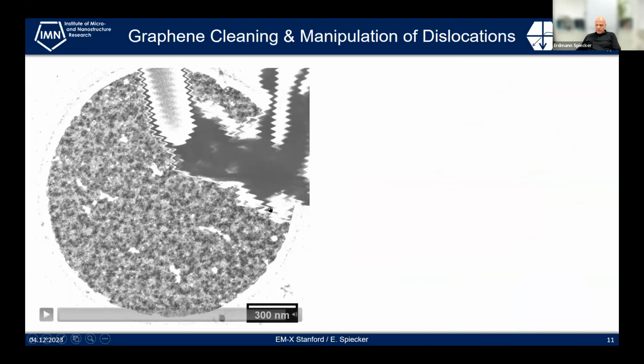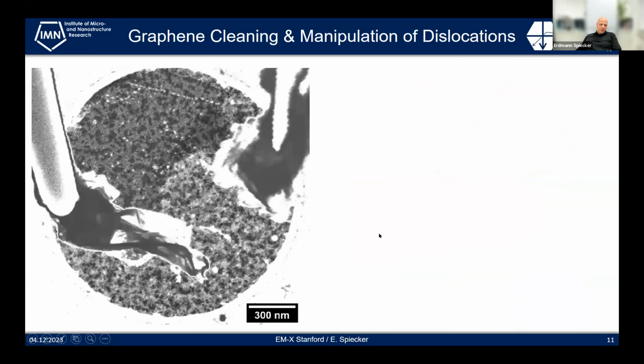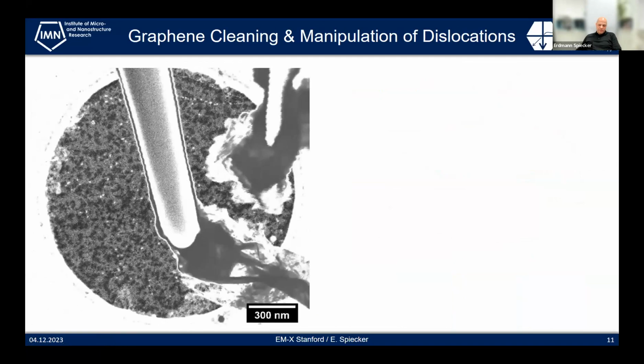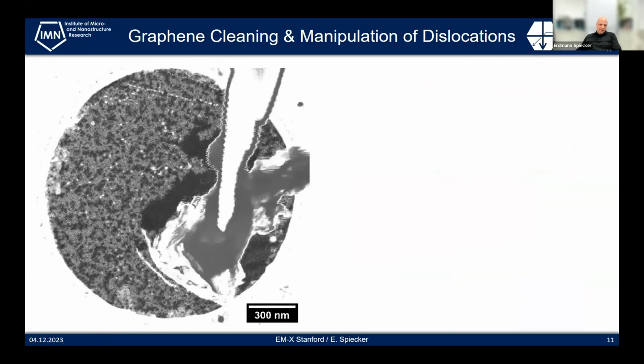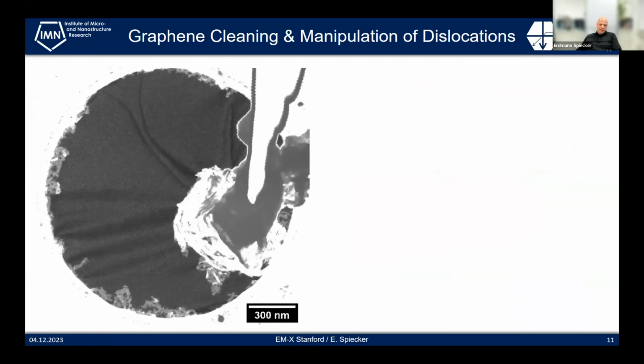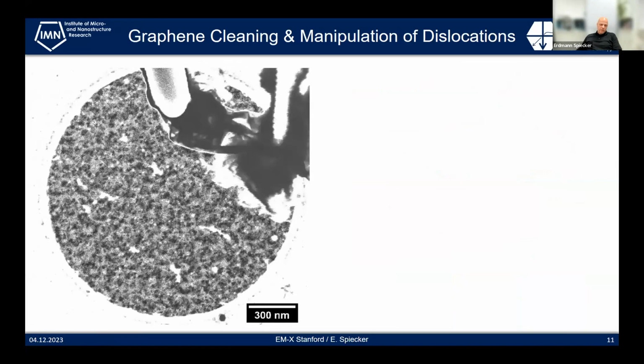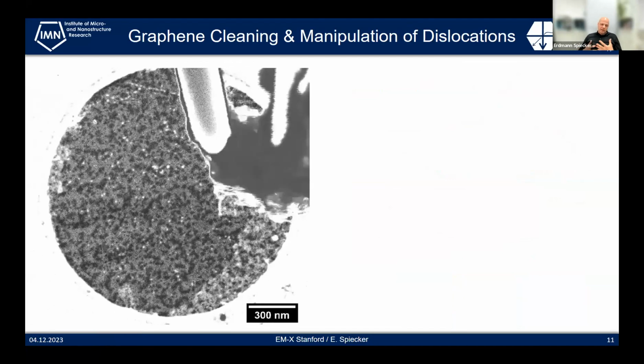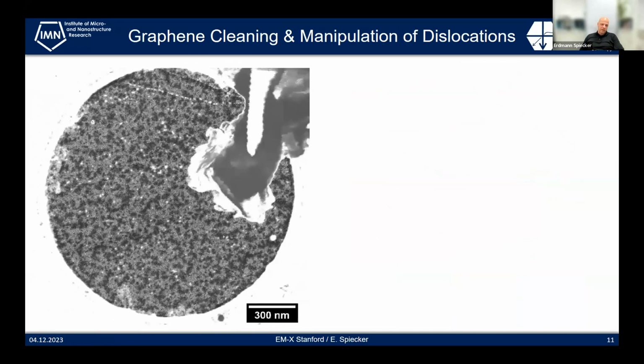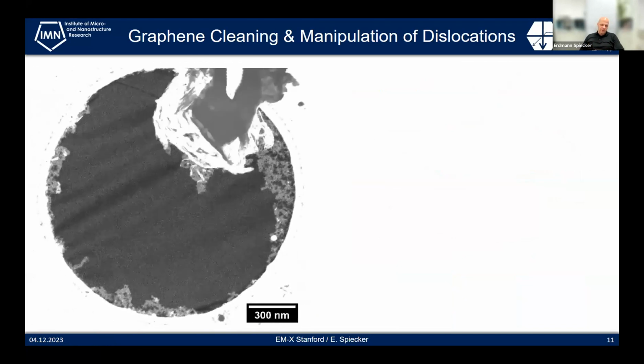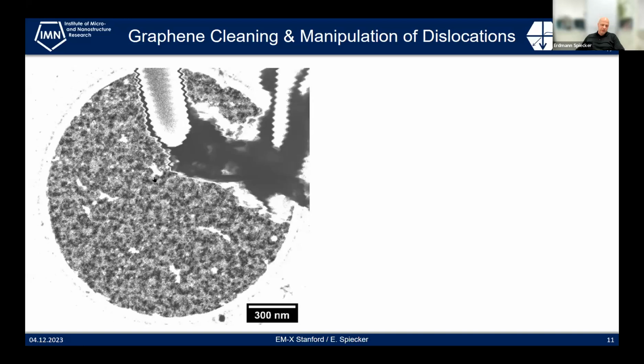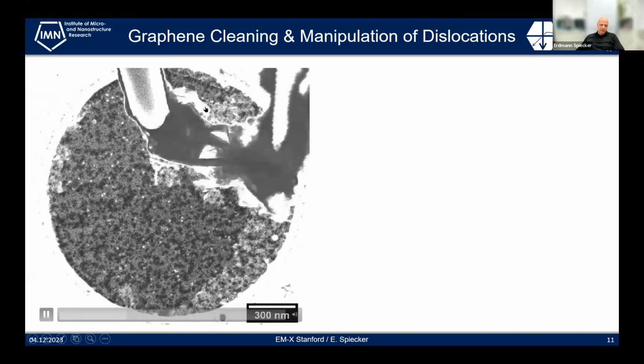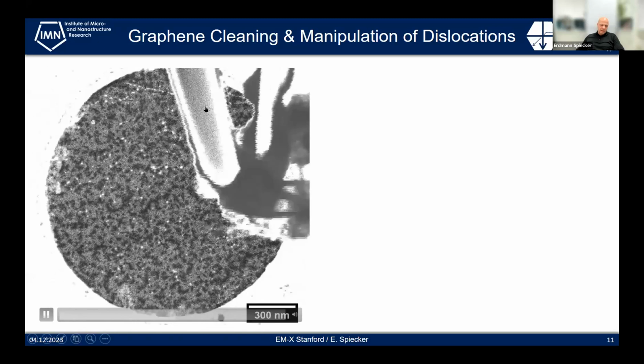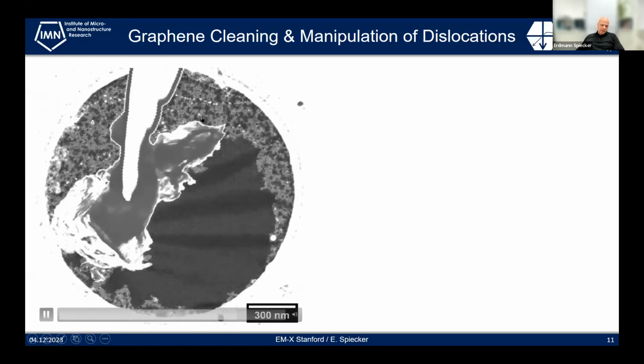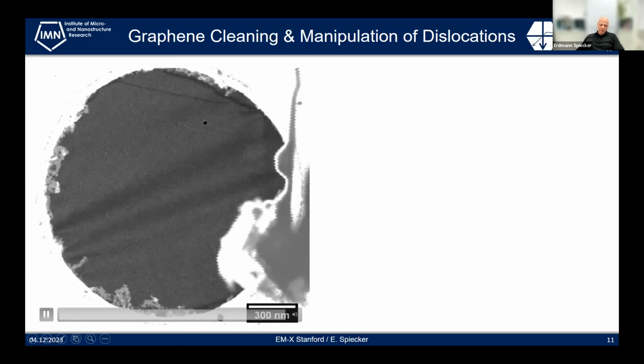In order to do that, we also developed a cleaning approach, and I show you here a video where we clean graphene with a manipulator from one side and then from the other side. And we could also do that in the TEM, and could check that we really get atomically clean graphene or bilayer graphene. In this particular case, it's bilayer graphene, and you see already a contrast line on the top side now in a second. And these are dislocations that were displaced by the tip.